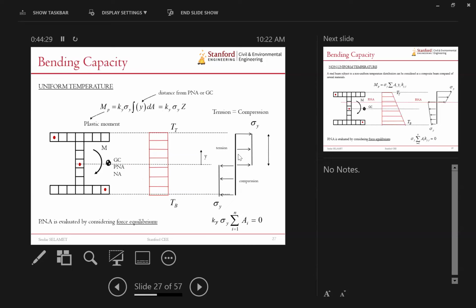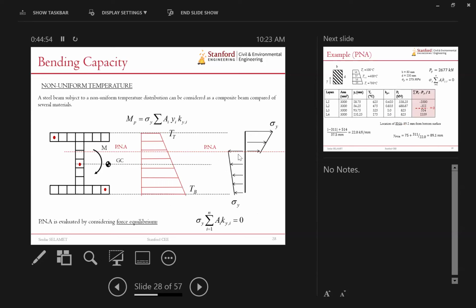So the bending capacity here is for uniform temperature. Again, the geometric centroid, PNA and NA will stay at the geometric centroid. The PNA is evaluated, as you guys might know, so that the net axial load should be equal to 0, but the area should be divided into two equal parts, tension and compression. But it's not exactly the same when we apply the non-uniform temperature distribution. Now we have to put the k_y inside of that summation, and our PNA actually shifts again up to a cooler region, because that cooler region can carry more load than the hotter region.